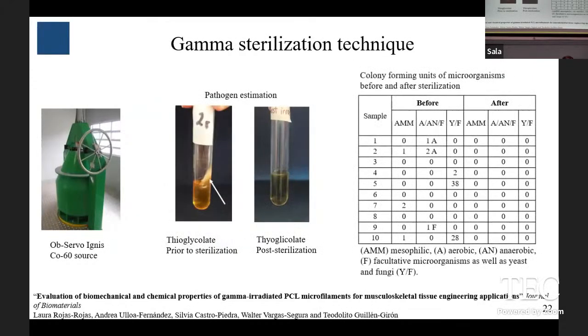Now I will go into the gamma sterilization technique. As I said, we wanted to be sure that the sterilization technique that we chose was working properly for our scaffolds. We used this equipment that is available here, and we chose to use 25 kilograys of gamma rays. First, we did a pathogen estimation, which means that we counted if there were pathogens present on the samples after irradiation, and results show that, for example, in this image, the thioglycolate is clear of pathogens after irradiation.